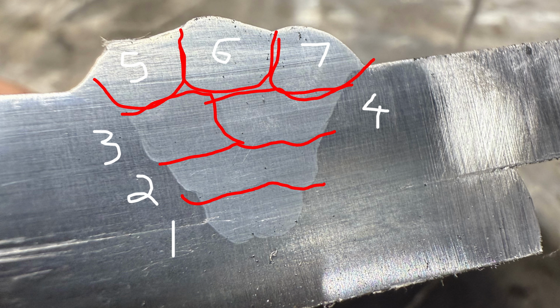So generally, your second pass is going to be a weave, even with stick, wire welding, TIG, same deal there. Now, pass number 3 is a stringer, and then number 4 is a very small weave. As you can see, size-wise, it's between pass 3 and 2. Again, this doesn't look that bad other than the area by number 4 and a little bit below that. I don't like the way that looks. That's generally not a good sign. Even part of 7 has a straight line in it, so that's undesirable.